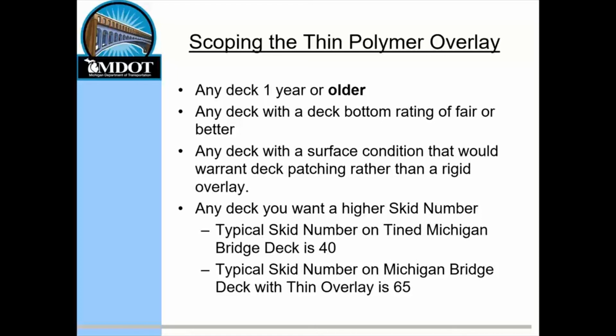For our older decks, we look at any deck with a deck bottom rating of fair or better. If your deck bottom is already bad, why bother? We also look at a deck surface whose condition doesn't require more deck patching than would call for a rigid overlay. Also, on some of our older decks, the tining is worn off or never had tining to begin with. We're just looking for a general increase in our skid number. Typical skid number on a tined Michigan bridge deck is only 40. Typical skid number on a Michigan bridge deck with our thin overlay system is 65. We don't use calcined bauxite on all of our thin polymer overlays, so this is just with our standard aggregate.